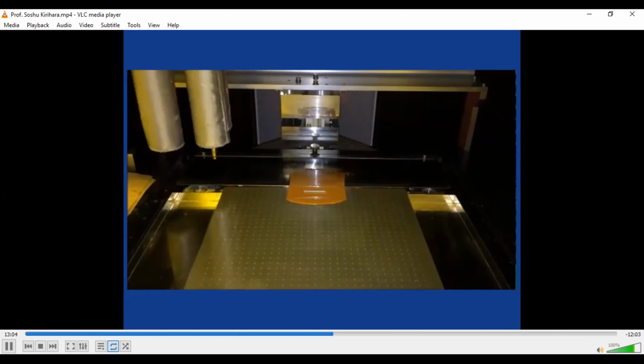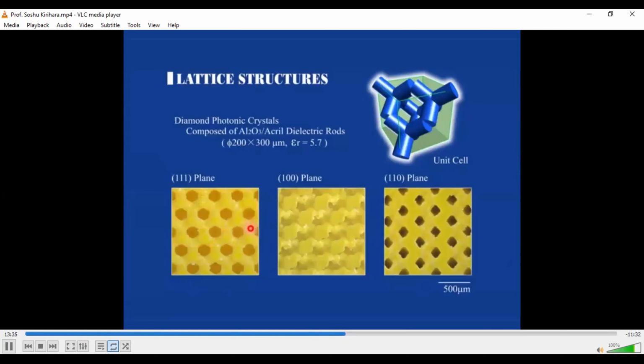Okay, this figure shows fabricated micrometer-order photonic crystals. In this case, alumina particles are dispersed in an acrylic resin matrix, and the volume fraction is 40%. You can see the micrometer order. The diamond lattice was obtained by using a laser scanning stereolithography process. Of course, these are composite materials, so we have to create a full ceramic micrometer-order lattice.